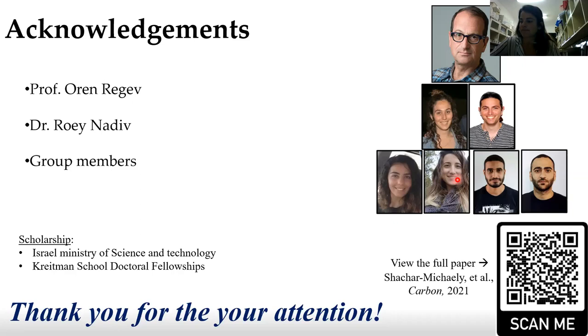Great talk. Does anybody have questions? I come from the field of carbon nanotubes and dealt a lot with the problem of dispersion and surface treatments. Could you tell me, did you do any surface treatments like functionalization? We use the NC7000 CNT, where we first did a sonication process of one hour with F127, then used centrifuge, took the supernatant, put it in a lyophilizer, and then used it in our composite material. We actually see that it disperses pretty well.